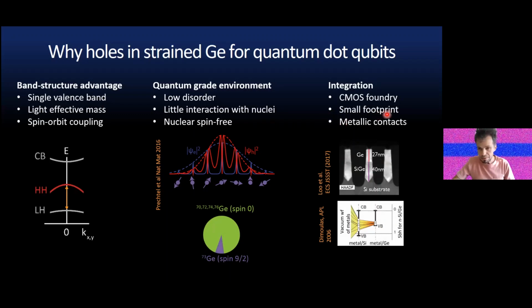The last element, which is very important, and I will spend quite some time on this, is the fact that you can make direct contact between metals and the hole gas, because basically every kind of metal tends to have its Fermi level pinned to the valence band with germanium. This is also the reason why it's very difficult to contact electrons in germanium and not holes. And this doesn't really happen in silicon.